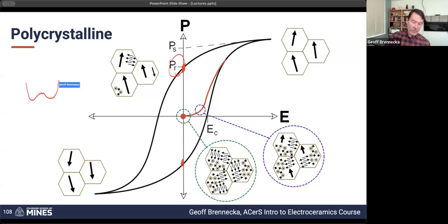We never get back to that completely random starting point because what's happening here locally is we've got that free energy barrier where every time we switch, we have to hop the ions over that barrier. And when there's enough of them, that barrier represents these remnants where things are just going to be perfectly happy sitting on this side versus that side, because the positive remnants and the negative remnants are equally likely. And that's what gives us our time-dependent, history-dependent response: we can push everything into one of those energy barriers and just let it hang out there.